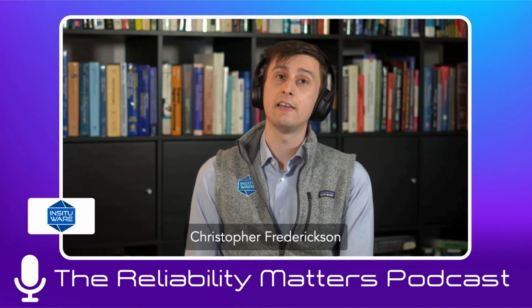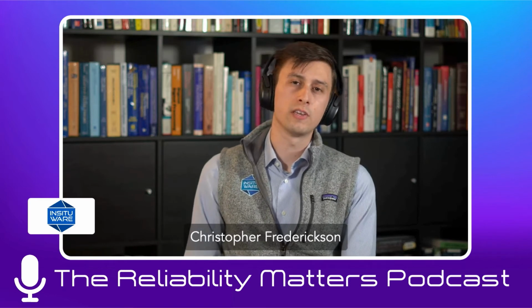Yeah, absolutely. So what we do for conformal coating measurements is we're using a technique called low frequency dielectric spectroscopy. So what this tells you is we're looking at the impedance of that conformal coating that varies depending on how it's thinned, for instance. So you can use this measurement to understand if that coating has been thinned appropriately, if you're doing that in your process, to make sure that the solids content is correct. And it's also sensitive to things like the conformal coating being degraded and partially cured in the container, or contamination with moisture, for instance. So we're using this low frequency dielectric spectroscopy measurement to look at a couple of different phenomena that occur within that coating.